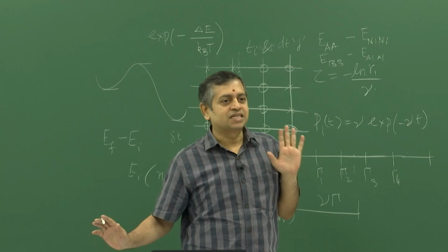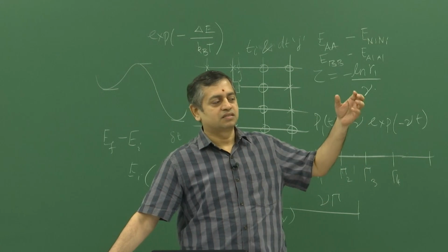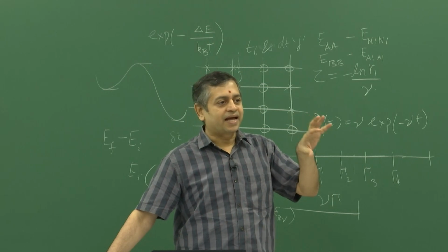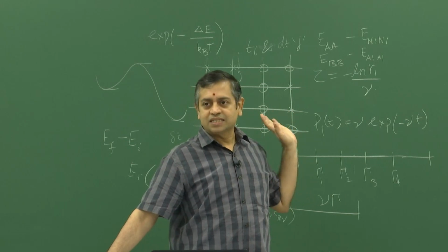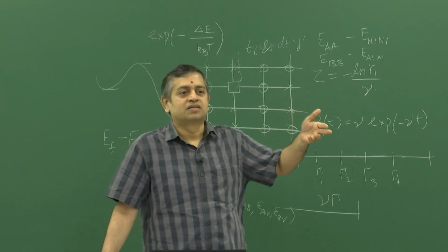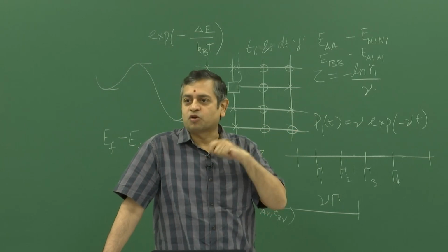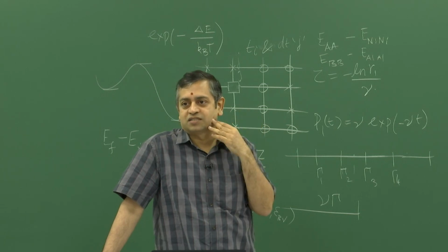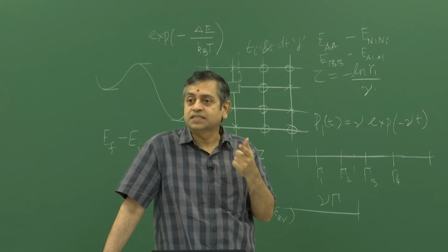So, that is the key word, we are just estimating these parameters, assuming just nearest neighbors and just pair interactions, and asking whether I can capture the energetics associated with this system. Generally it will scale: high melting, you will get larger energies because cohesive energy is high; low melting, smaller. So, correspondingly thermal effects will be captured in your model because you have energies which scale accordingly. Okay. So, that is how you think about it. Any questions?